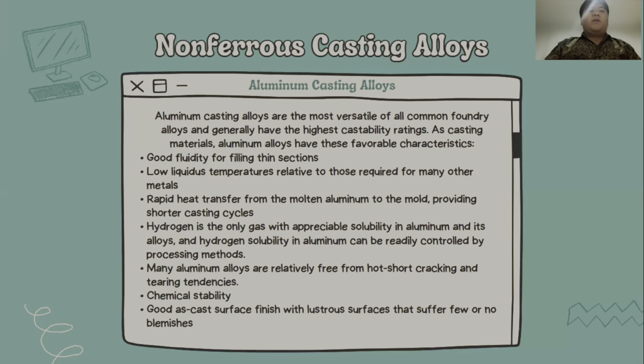Hydrogen is the only gas with appreciable solubility in aluminum and its alloys, and hydrogen solubility in aluminum can be readily controlled by processing methods. Many aluminum alloys are relatively free from hot short cracking and tearing tendencies. Chemical stability, and the last one is good as-cast surface finish with a lustrous surface that suffers few or no blemishes.